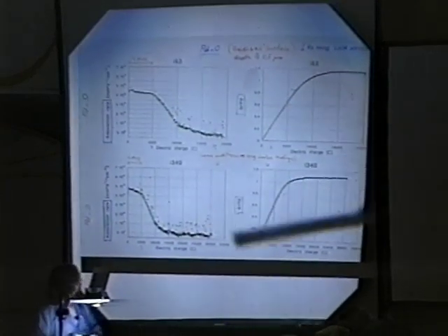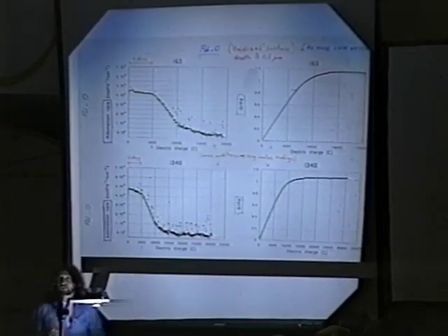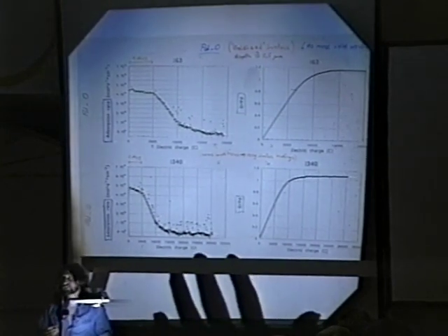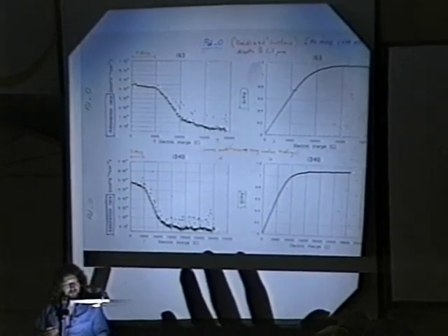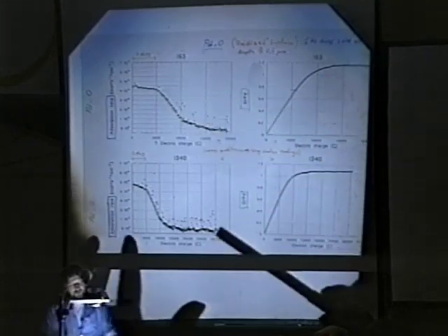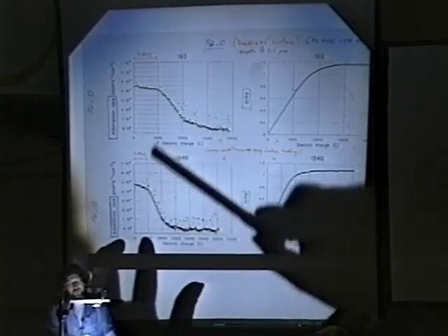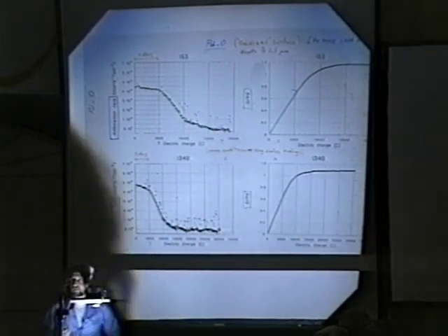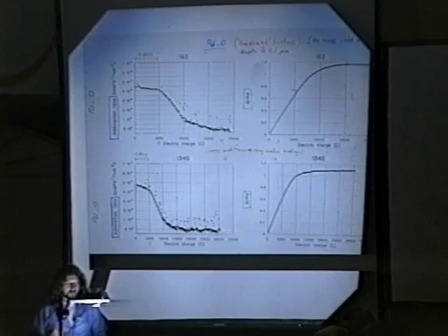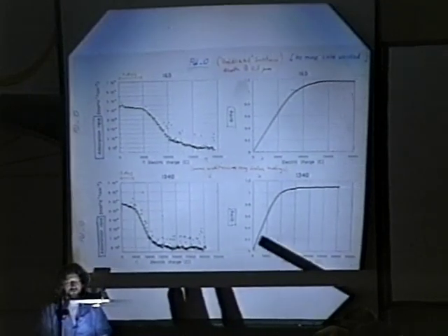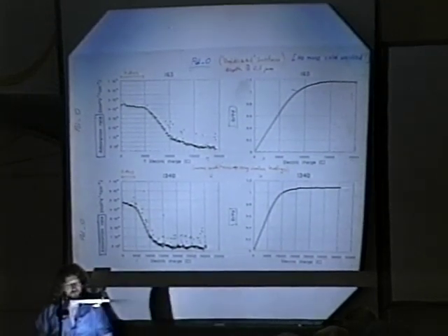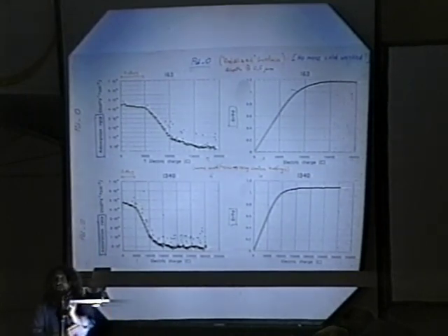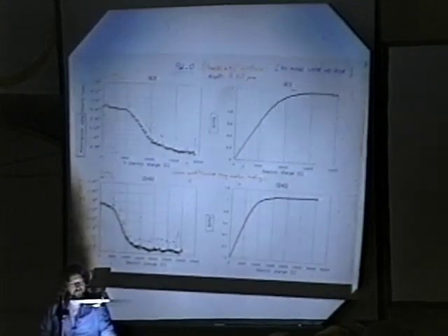These are two plates oxidized with the same procedure, and they have this. Okay, the scale is different now, but this is 1 day. So you can see the profile is very similar, and also the loading ratio. So it means this procedure can be repeated as many times as we like, and we have the same results.